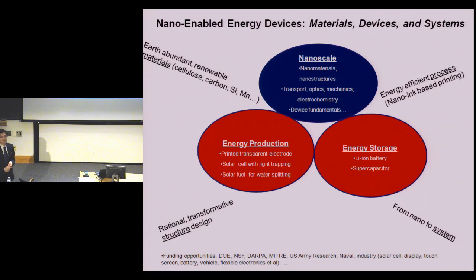Do you need to keep the cellulose around? Sorry, but after you create the cellulose, is it possible to dissolve the cellulose or retain the structure? You don't want to dissolve cellulose. You want to disperse it. You want to maintain the one-dimensional structure, because that structure will help you get scattering of the light. That's what I mean by light trapping. Because if you have a continuous cellulose film, that will be like a plastic. There's no advantage in terms of light management.